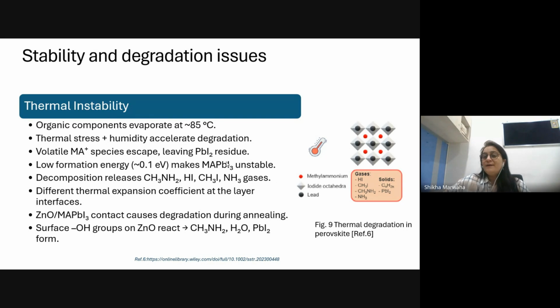This lead iodide again has lead, and this residue that is left behind is of no use, because this process is irreversible. We cannot reverse this because the gases are volatile. And why is this happening? Because the formation energy of this methyl ammonium lead iodide is quite low, so it's quite unstable.